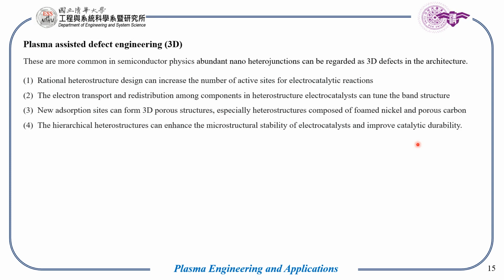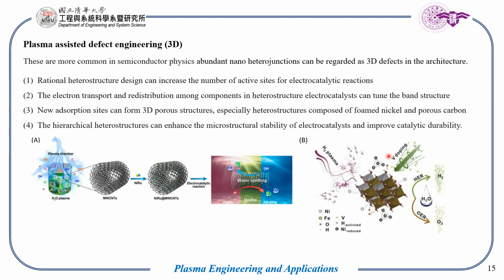Coming up to 3-dimensional defects that are caused due to plasma. Here we can see the researcher named Peng, who employed a solution plasma reduction to construct metal nanoparticles that attach to the functional carbon sites, and these catalysts were composed of nickel and ruthenium alloy nanoparticles enriched in carbon nanotubes. And further, it was used for HER and OER reactions.